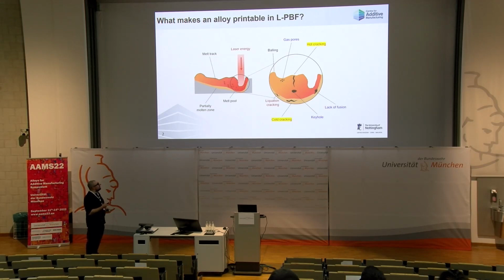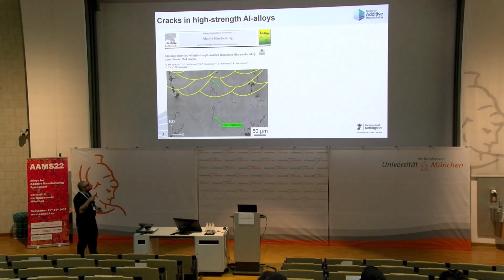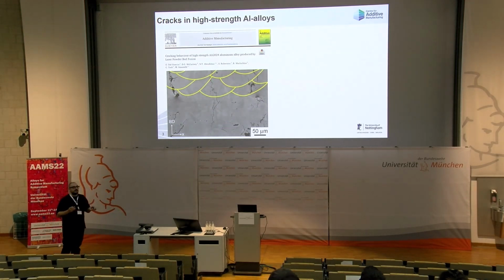But also from a material point of view, this is quite interesting, because hot cracks, as you can see, and cracks in general are very, very detrimental for high-strength aluminium alloys. So I started working with 2024, quite a known aluminium alloy, a couple of years ago, and we studied the cracking behavior of this alloy, and we found out that there is not actually just one cracking mechanism, but there are at least two of them, at least in this class of materials.